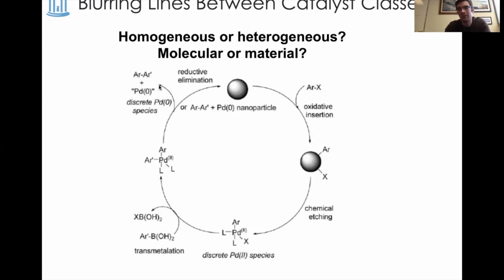So what appeared to be a heterogeneous catalyst in the classical sense of palladium metal nanoparticles actually, in fact, is leaching small, well-defined, homogeneous molecular catalysts that can either continue on a molecular cycle or reform nanoparticles, and you've got this very dynamic system going on. So I think that's a really fascinating example that also blurs the line between these catalyst classes.